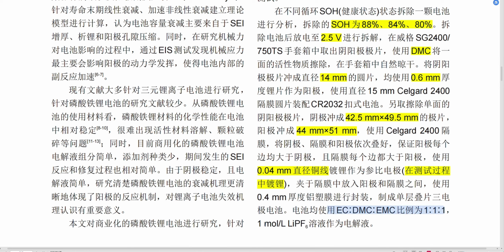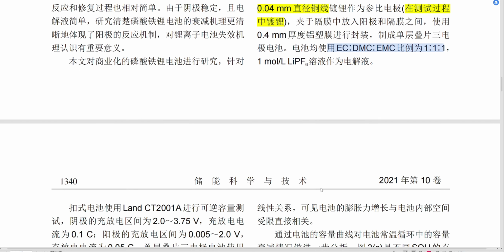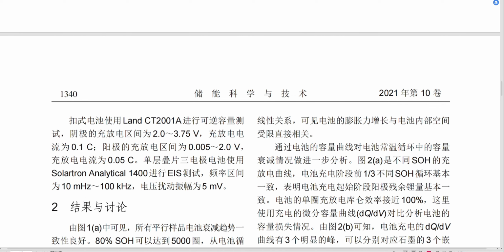And then their electrolyte is EC, DMC, and EMC solvent with 1 molar per liter LiPF6. For the coin cell, the half cell of the cathode side, they cycle at 2 volt to 3.75 volt with a cycling current of 0.1 C. For the anode side half cell, they cycle at 0.005 volt to 2.0 volt with 0.05 C, which is C over 20.